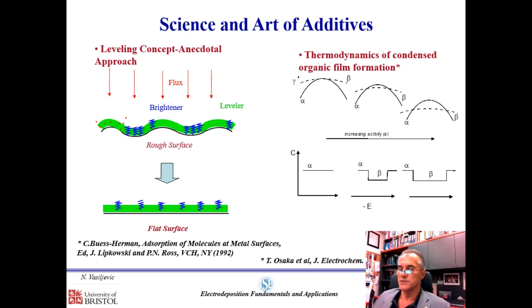And the general description goes that we always have some kind of a duality of the roles, where the leveler forms a film on the surface, which is difficult for metal ions to penetrate, and then the brightener locally perturbs this film in specific regions where we have the valleys. And as it perturbs this layer, the ions have an easier path to go through this perturbed part of the layer and reduce on the surface, which basically creates the outcome where the surface gradually smooths out and becomes highly reflective.